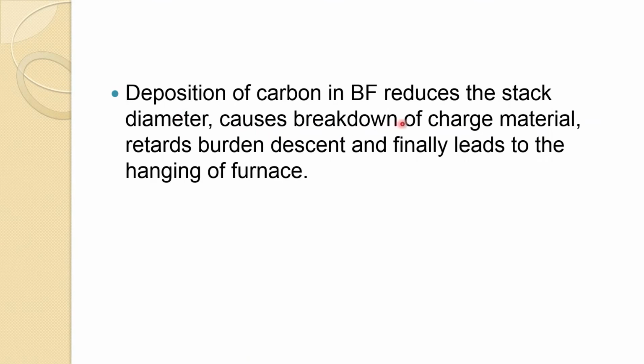That causes breakdown of charge material, also retards burden descent, and finally leads to the hanging of the furnace. These are the major problems which occur due to the deposition of carbon, and one has to be careful and design the blast furnace reaction or the temperature zone in a way that it should be minimized. One cannot completely get rid of this, but it should be minimized.